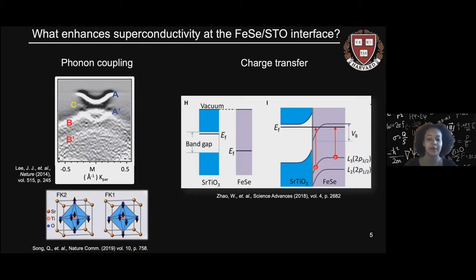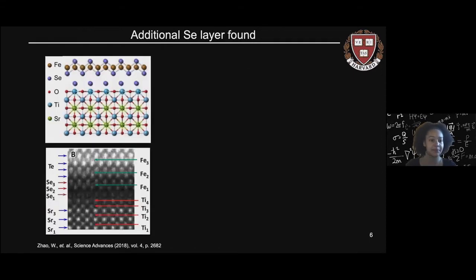The second prominent mechanism proposed for superconductivity enhancement is charge transfer. So here an experiment demonstrated band bending between the strontium titanate and iron selenide monolayer, which is known to cause charge transfer. It's proposed this charge transfer may produce a doping effect that would lead to the system's superconductivity enhancement. But in order to understand what causes these effects, various studies have attempted to image the interface.